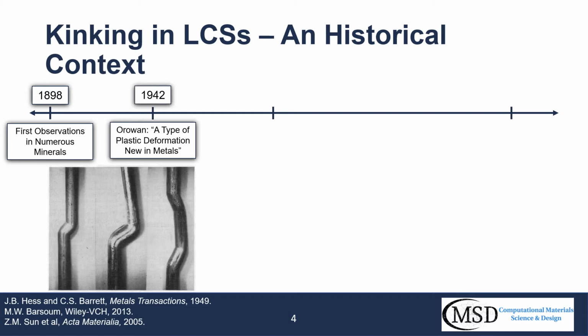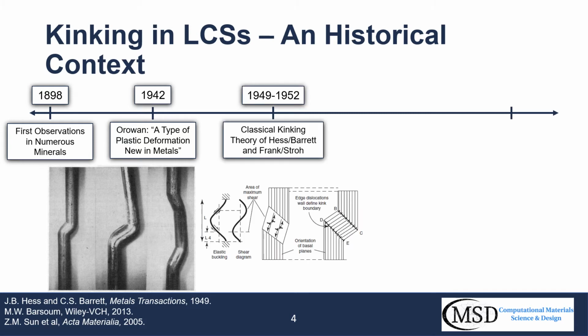Moving forward to the 1940s, Orowan observed kinking in single crystals of HCP metals loaded parallel to their basal planes. He declared that this was an entirely new type of plastic deformation when dislocation glide was inhibited. Soon thereafter, however, Hess and Barrett repeated some of Orowan's experiments and asserted that kinking could indeed arise from a combination of elastic buckling and subsequent nucleation of dislocation dipoles, which would then glide apart to form the kink band and its associated kink boundaries.